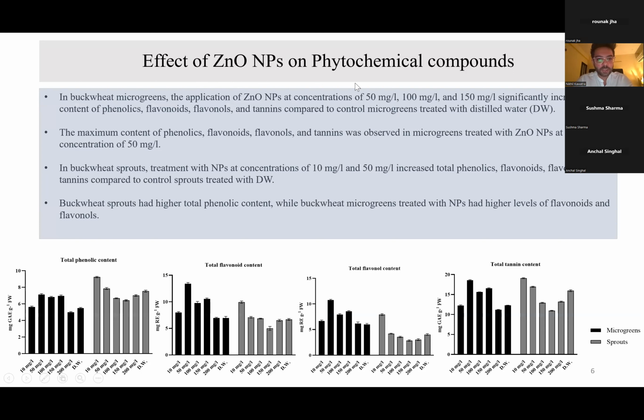After this, the effect of zinc oxide nanoparticles on the phytochemical compounds. In the buckwheat microgreens, the application of zinc oxide nanoparticles at different concentrations of 50, 100, and 150, it significantly increased the content of various phenolics, flavonoids, flavonols, and tannins. The maximum content of these compounds was achieved at a concentration of 50 mg per liter in microgreens. Whereas talking about sprouts, the treatment of nanoparticles at a concentration of 10 and 50 mg per liter increased the content of phenolics, flavonoids, flavonols, and tannins. Comparing the two, microgreens and sprouts, the buckwheat sprouts had a higher content of phenolics as compared to microgreens, whereas the microgreens contain more amount of flavonoids and flavonols in comparison to sprouts.